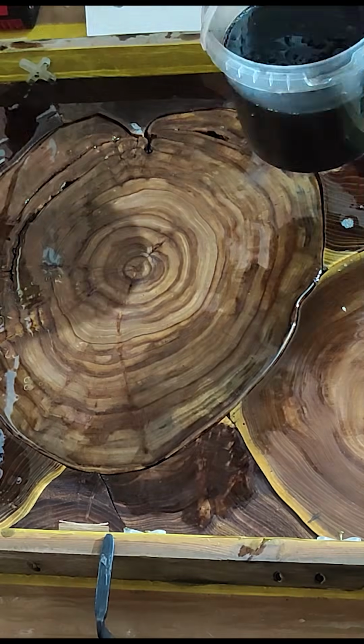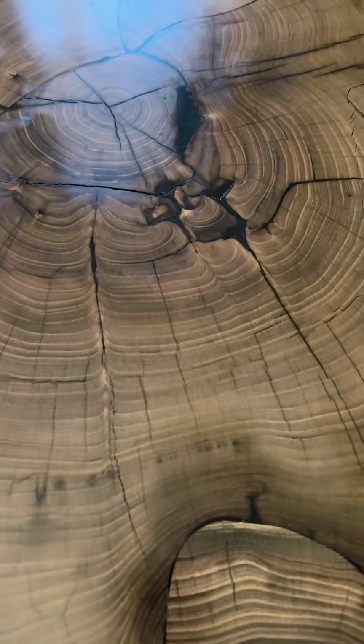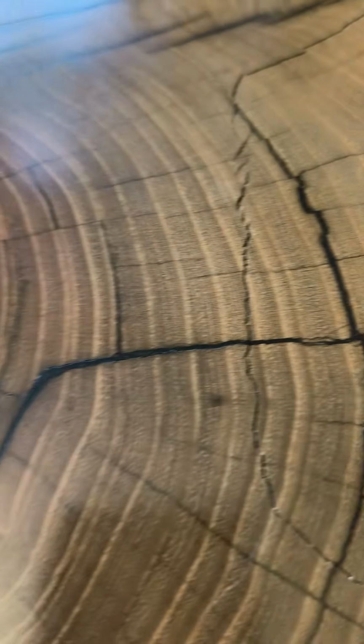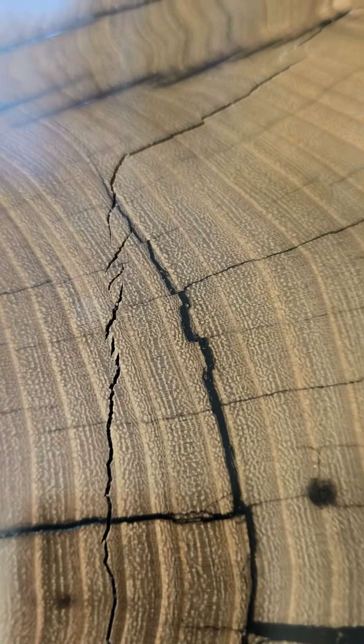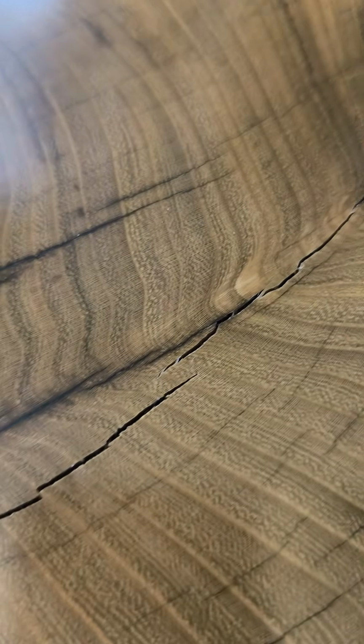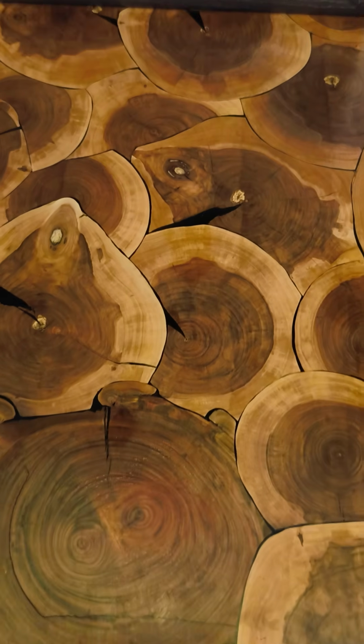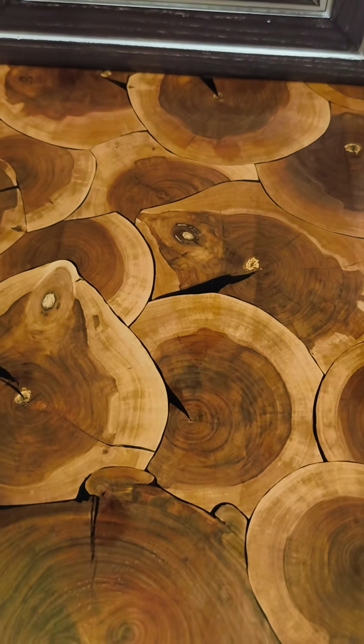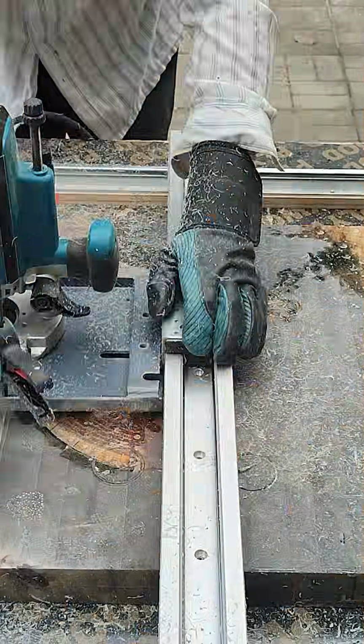The amount of shrinkage depends on the type of epoxy and additives, but some degree of shrinkage is always there. And all of this creates internal stress inside the piece, which means warping is very likely, and cracking is always a possibility. If you're building something for yourself, no big deal. But if you ship a table across the world, fixing it later becomes a whole different story.